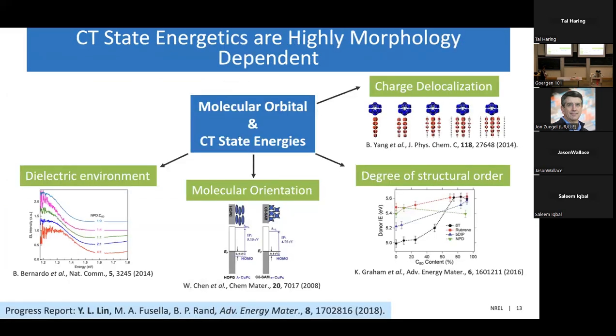And researchers have found over the years that both the molecular orbital energies as well as the interfacial charge transfer state energy is highly dependent on morphology. So it'll depend on things like the local dielectric environment at this interface, the molecular orientation, as well as the degree of structural order and the degree of charge delocalization at this interface.